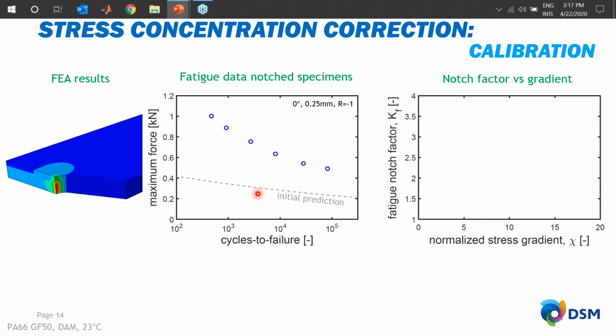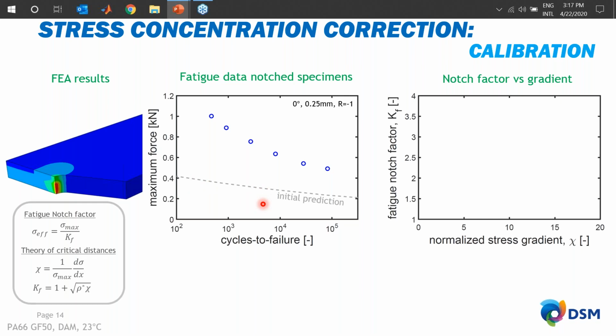But this is something which is known, and that's why we decided, okay, let's just do the things that they also use when they try to predict fatigue for metals, and that is to correct for these fatigue notches. So you can use a support factor or the fatigue notch factor to compute an effective load by scaling down the maximum local stress. And we decided to use the theory of critical distances, which uses the normalized stress gradient. So how fast does the stress drop on a path perpendicular to the maximum principal stress? And with this normalized gradient and a characteristic length, you can more or less define how severe this local stress concentration is.